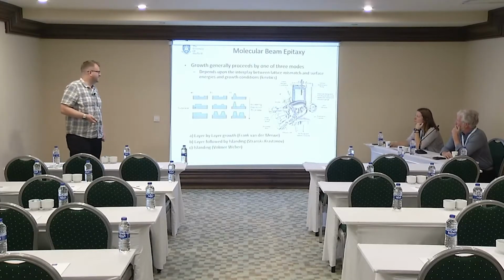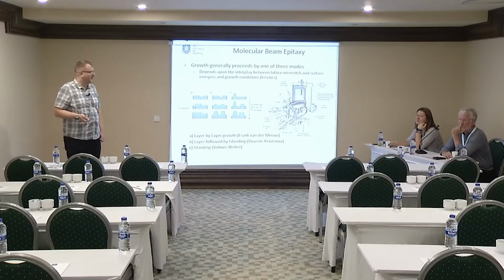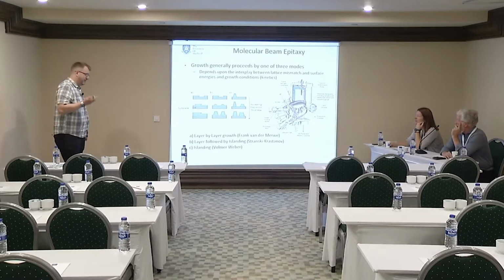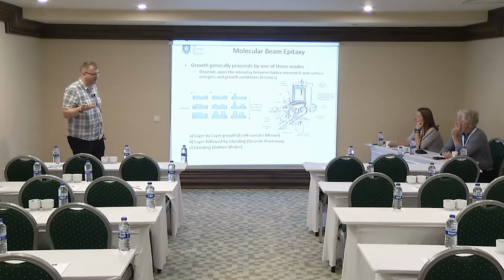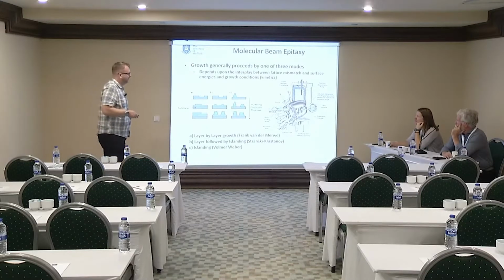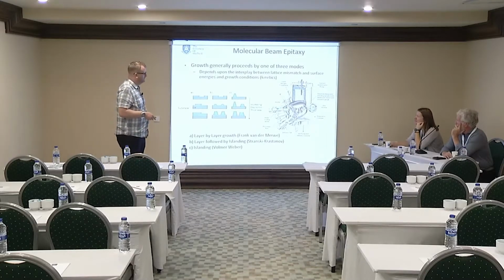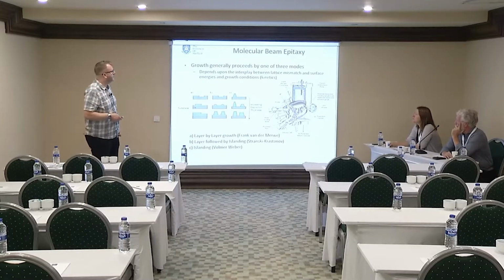We can skip a little bit through this, but molecular beam epitaxy, there are people here at this conference who do this, even Bozovic for one example. Effectively what we have is a vacuum system where we have individual heated sources which we evaporate onto the substrate, and we use shutters to mechanically open and close to control the material that we're growing.